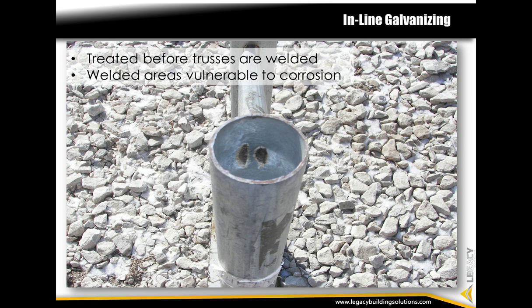Inline or pre-galvanized steel consists of a coating of zinc and chromate with a clear polymer top coat, also known as gator shield. Inline galvanized tubes are treated before the trusses are welded. During the welding process, the gator shield coating is burned off the inside and outside of the tubes. This leaves the welded areas, the most important areas to protect, extremely vulnerable to corrosion.